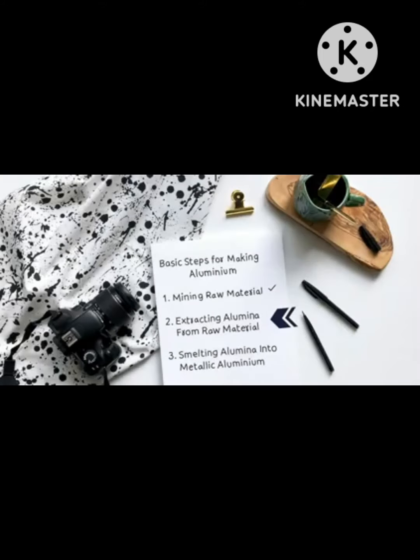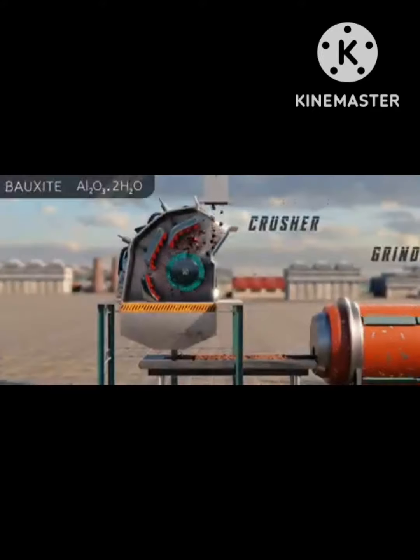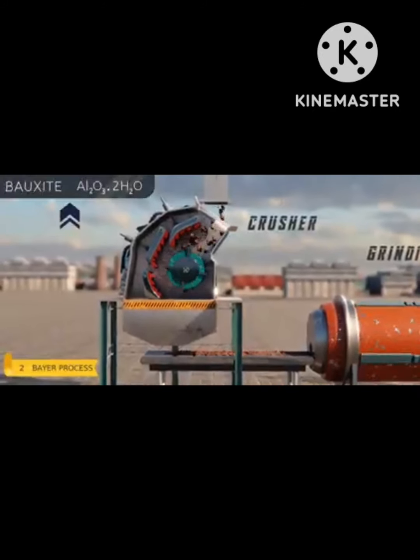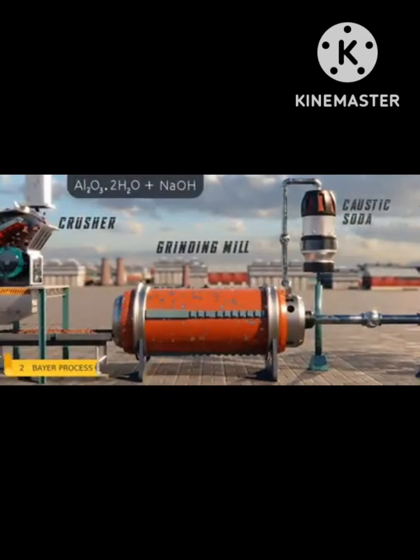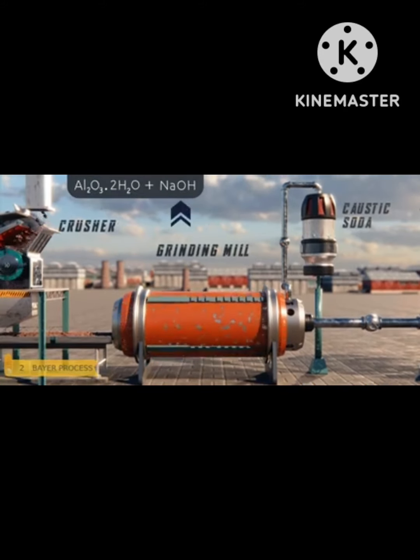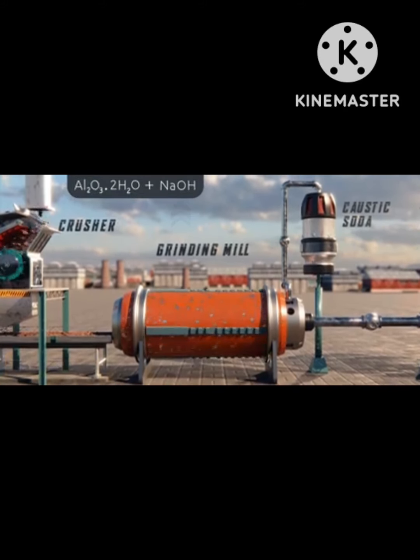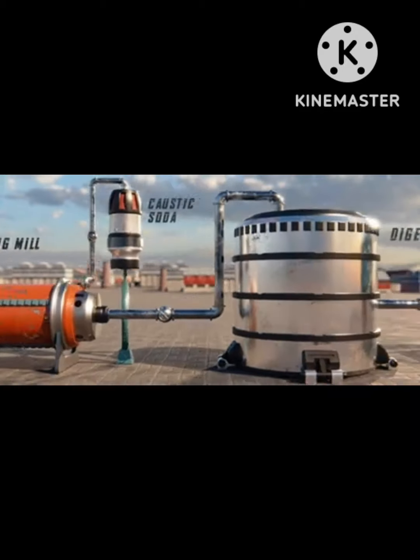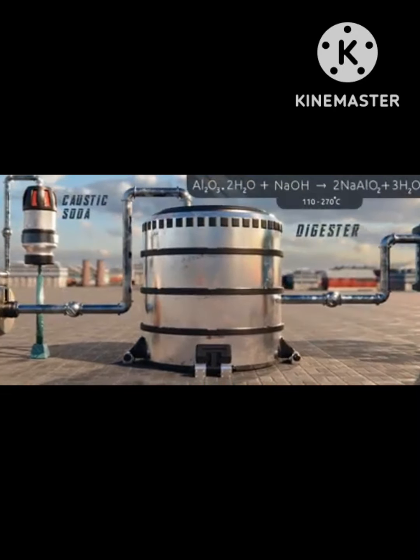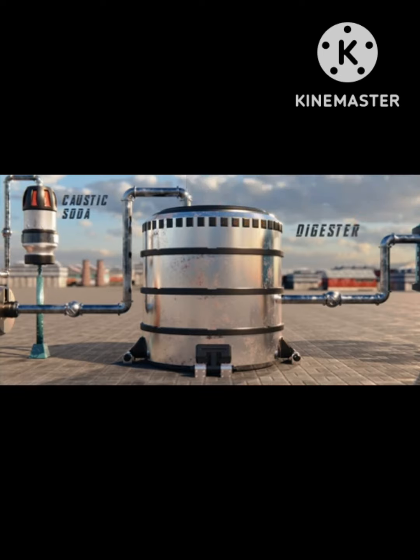And now step 2. Extracting alumina from raw material bauxite. First, the bauxite ore is mechanically crushed. Then the crushed ore is mixed with caustic soda and processed in a grinding mill to produce a slurry. Then the slurry is pumped into a digester. In the digester, the slurry is heated to 270 degrees Celsius under pressure. The caustic soda reacts with the aluminum compounds in bauxite material to produce a solution of sodium aluminate.